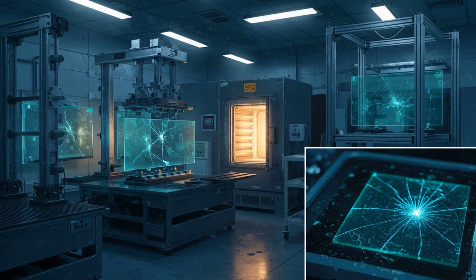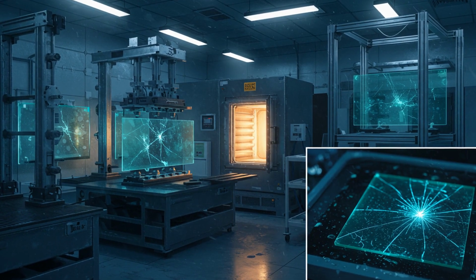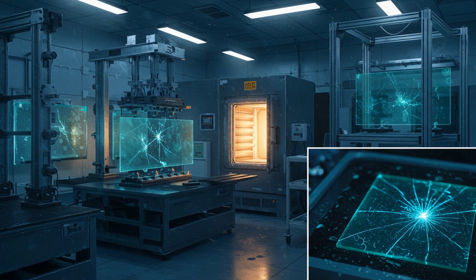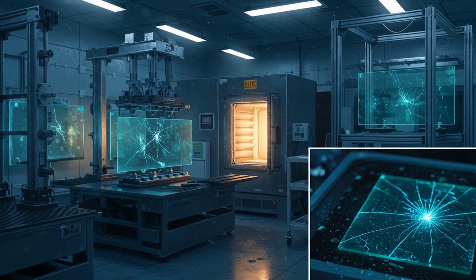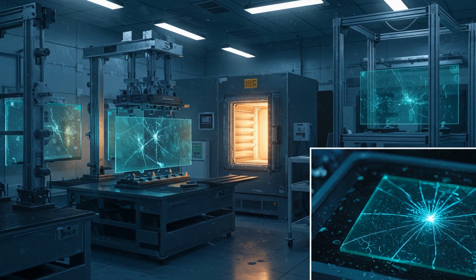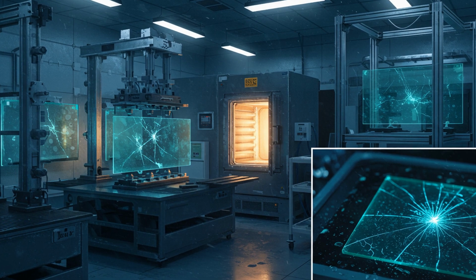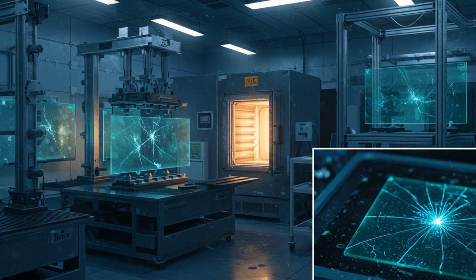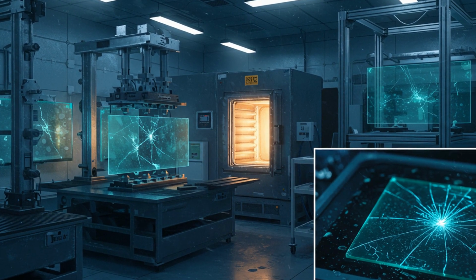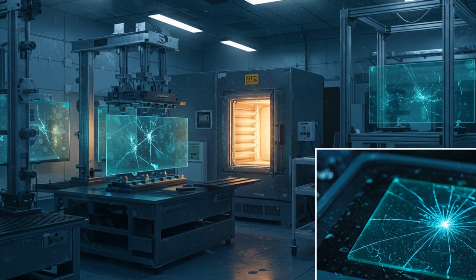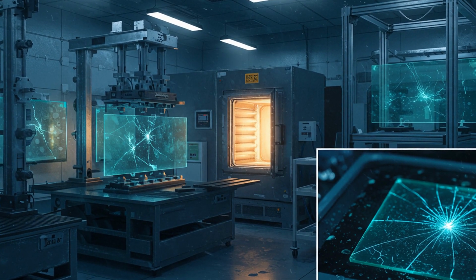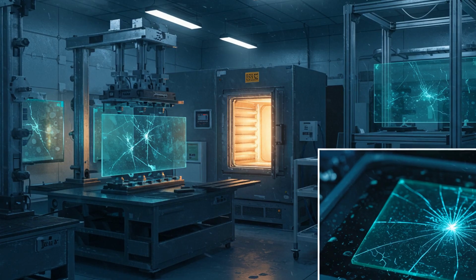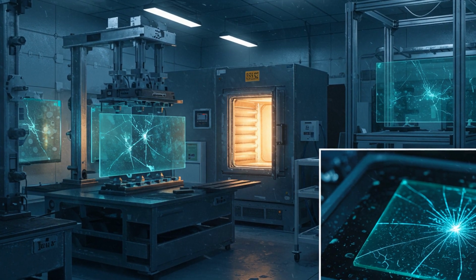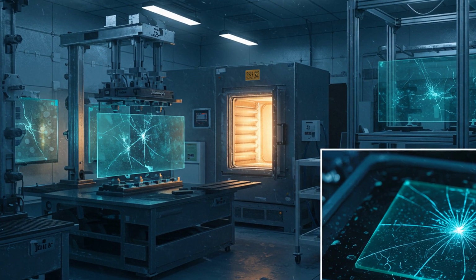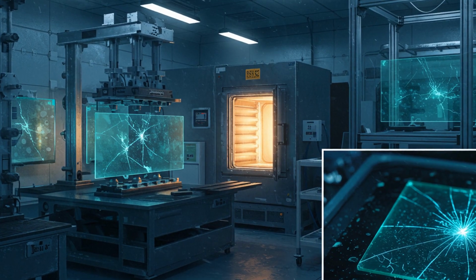Solar modules live outside and must endure years of storms, UV, and temperature swings. Testing protocols are rigorous. Thermal cycling exposes modules to repeated swings from below freezing to hot daytime conditions, often from negative 40 degrees Celsius to 85 degrees Celsius, checking for solder fatigue and delamination. Damp heat chambers hold modules at 85 degrees Celsius with 85% relative humidity for 1,000 hours, forcing moisture to reveal weak seals and ionic migration.